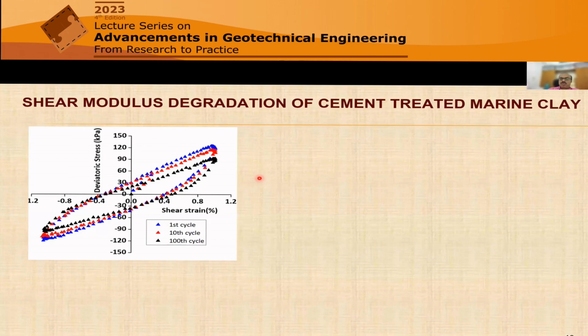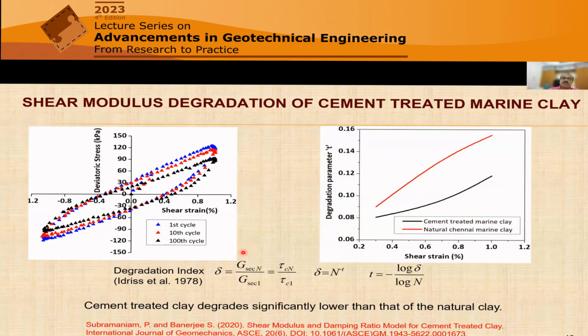Having said that, we compare with the pure clay situation. This comparison is done based on a well-known formulation, which defines an index termed the degradation index, which is the nth cycle shear modulus to the first cycle shear modulus. If you compare that on a logarithmic plot, there is a degradation parameter, and as you can see, the red line is of course natural Chennai marine clay, which has a very, very strong degradation behavior. That means with the number of cycles, it reduces a lot.